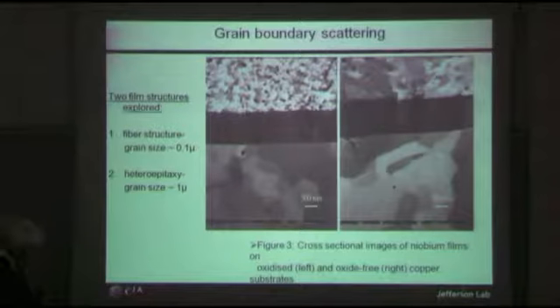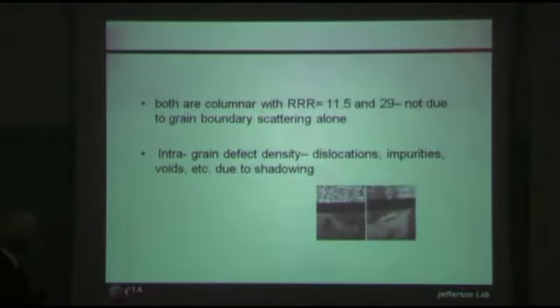I think I mentioned on the next slide, maybe, the mean free paths. Here they had one sample, this is a columnar structure. I'm sorry, they're both columnar, but this one is a fiber structure, and the other was a single heteroepitaxial. In both cases, the grain dimensions can't account for this kind of a triple R.